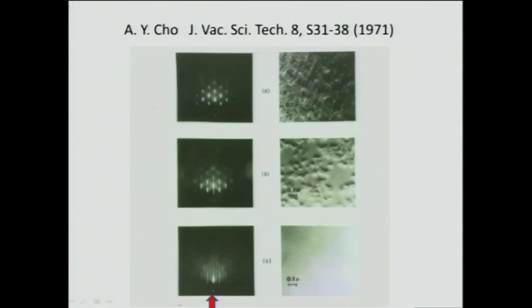And the electron beam, as I mentioned, is at a grazing angle on the surface. The electron beam has to penetrate through the protuberances of the microfaceted surface, and then the three-dimensional Laue condition has to be satisfied. At that time, there were spots. Therefore, you get spot diffractions.